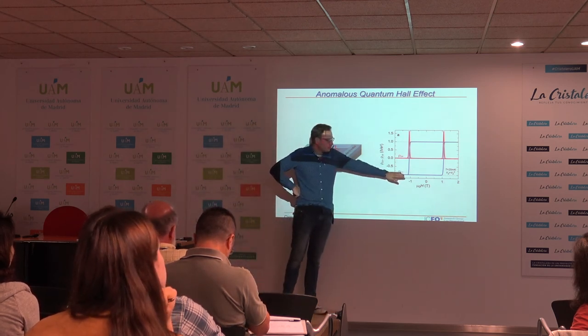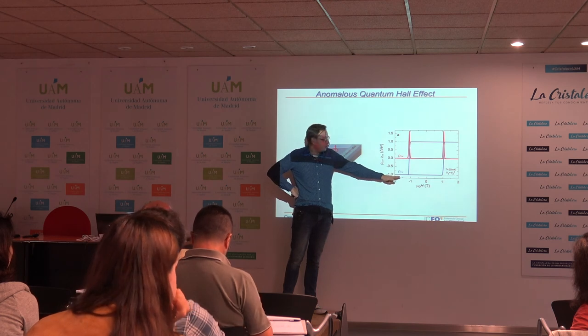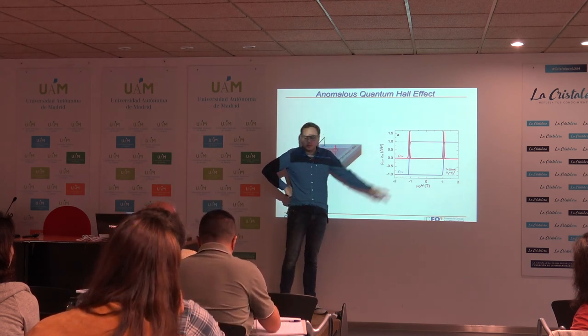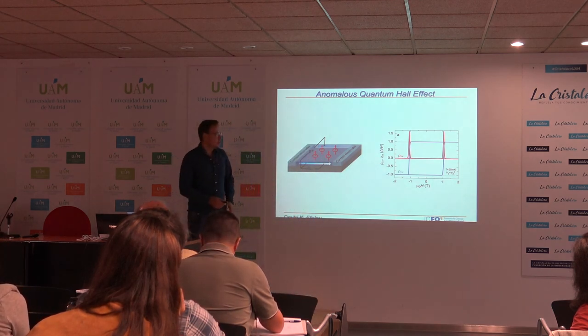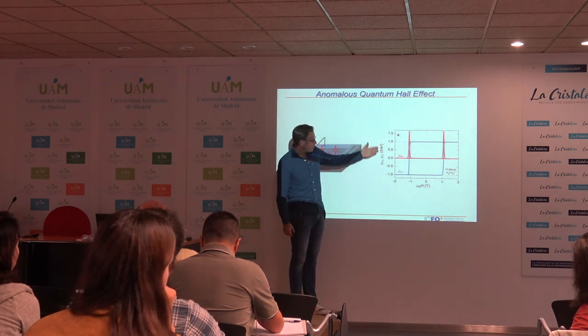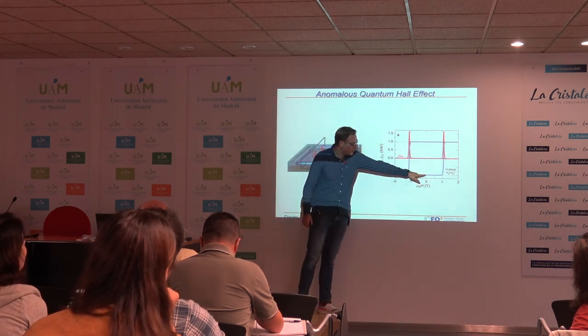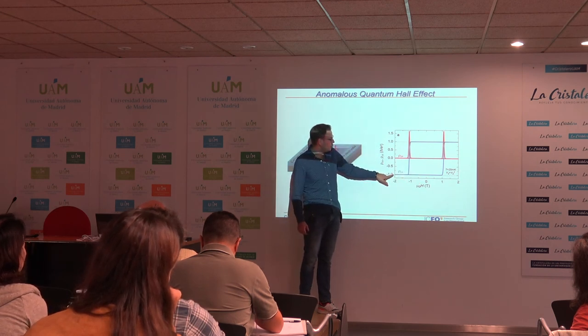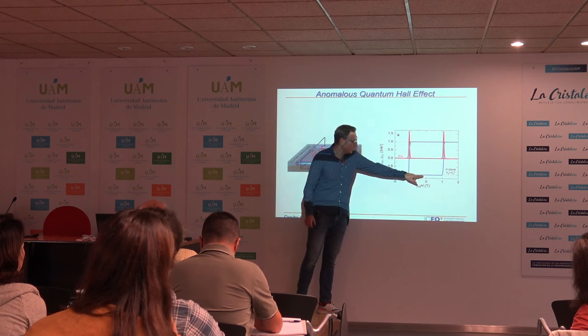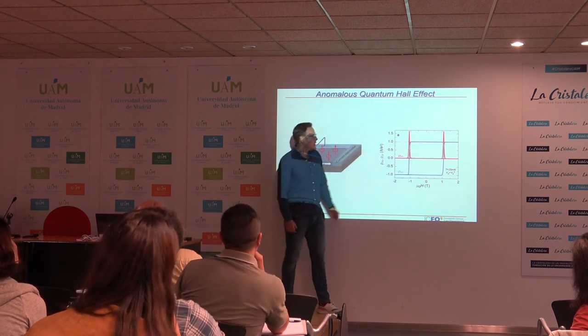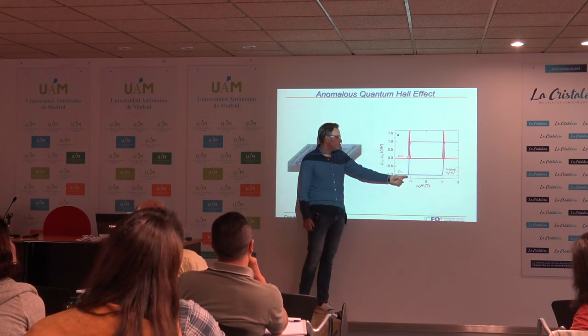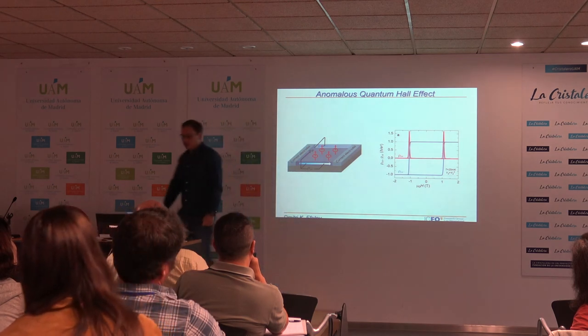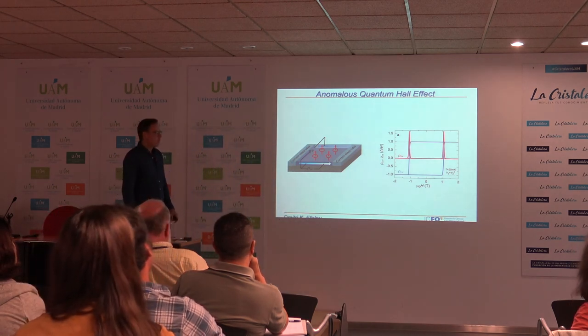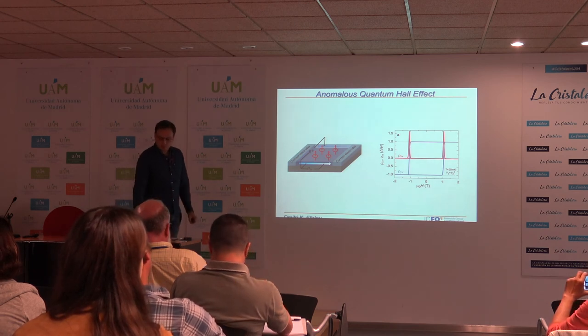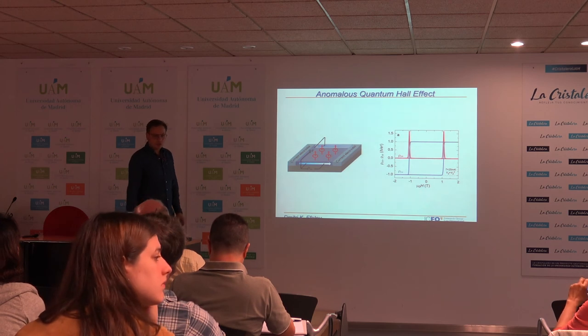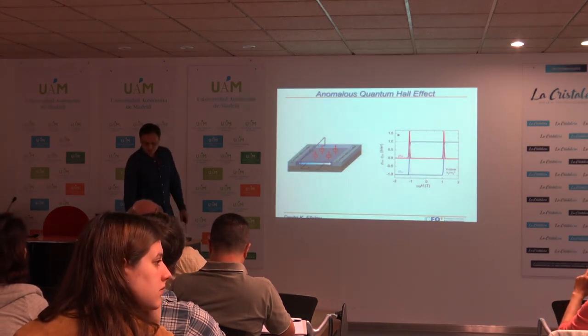What you're expecting is magnetism with quantized edge states appearing at zero magnetic field. So if you measure Rxy in the system, starting at zero field you have perfectly quantized edge states with h over e squared. Then if you increase the magnetic field, you can switch this edge state to plus one quantization or to minus one quantization, and you have this hysteresis in the system. This is exactly the scenario one might expect from twisted bilayer graphene, that one would find magnetic phases in some of these correlated insulating states.